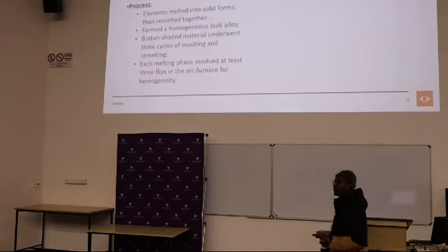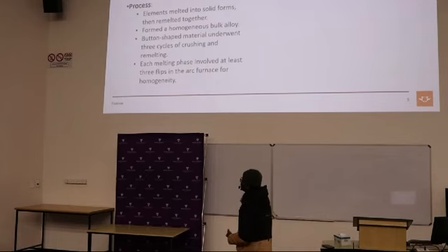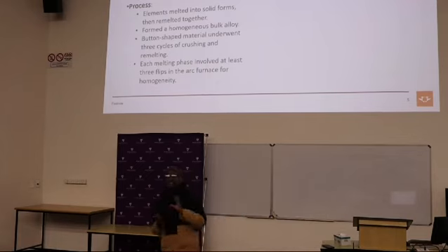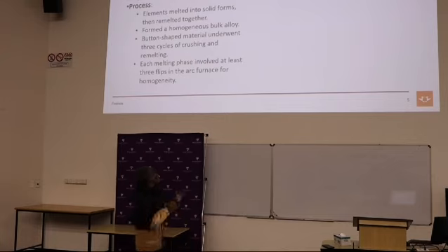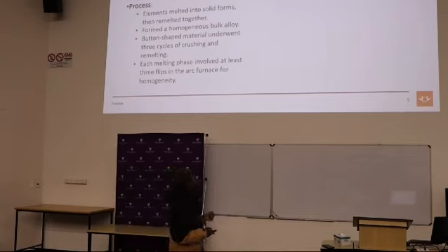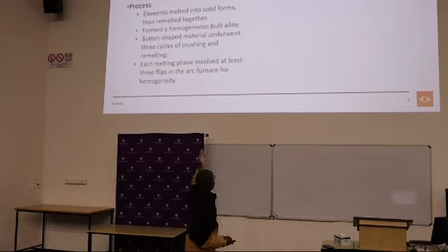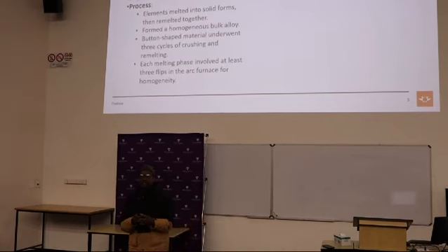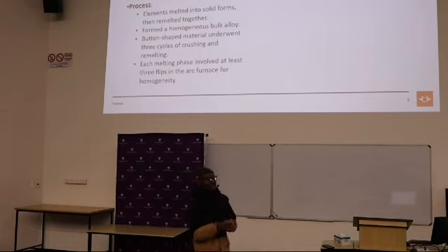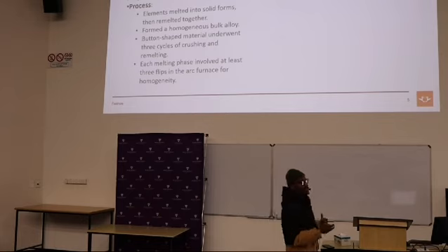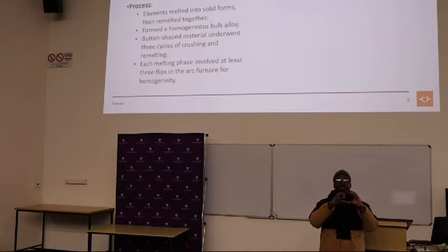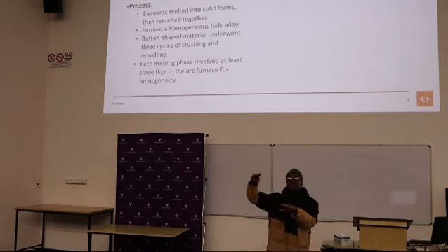Now, how did I synthesize these materials? We used the arc melting technique, where we used high purity elements, approximately 99.99% purity: molybdenum, rhenium, and of course chromium. In terms of the synthesis, the elements were powdered first, then pressed using a drill press, and melted together in an arc furnace. In that process, they formed what are called buttons, or button structures.